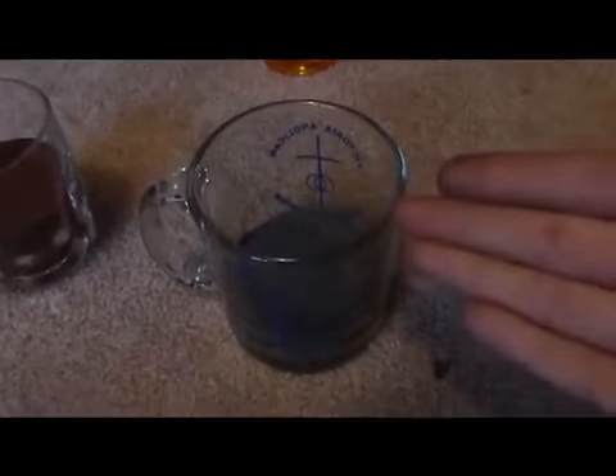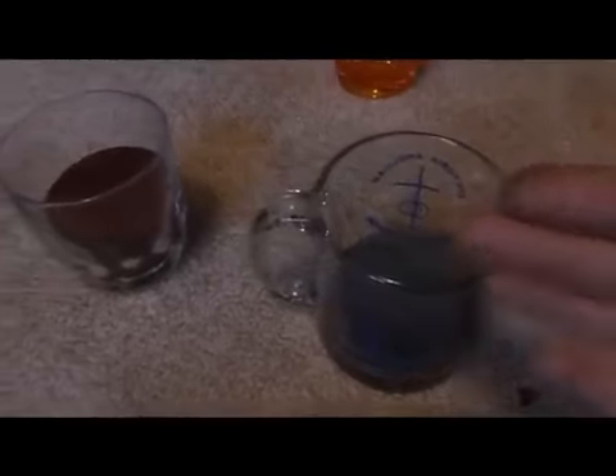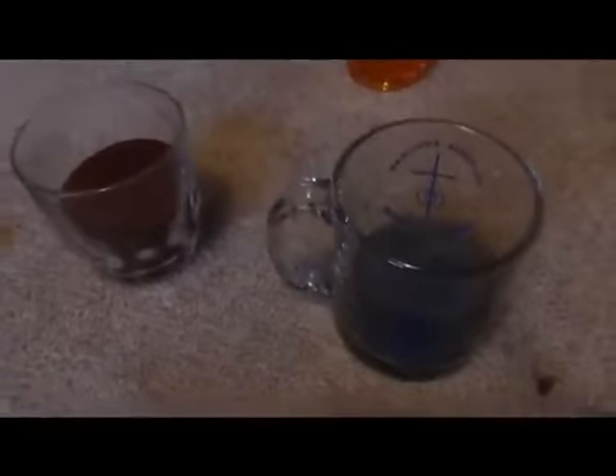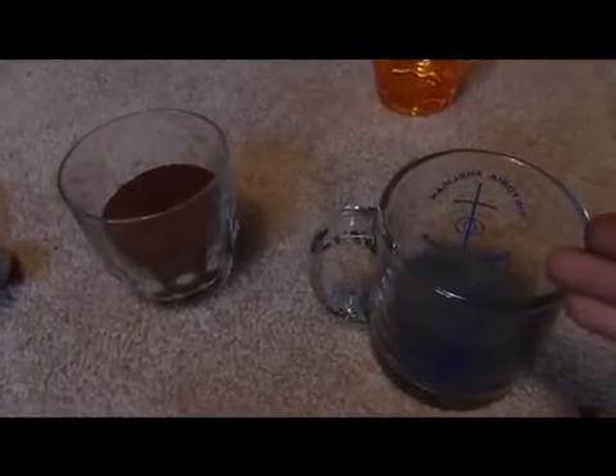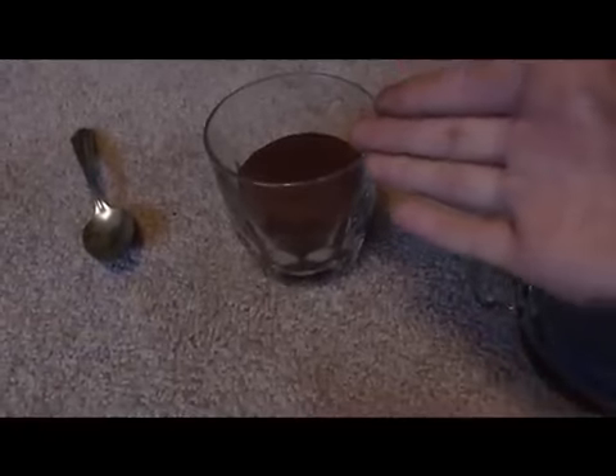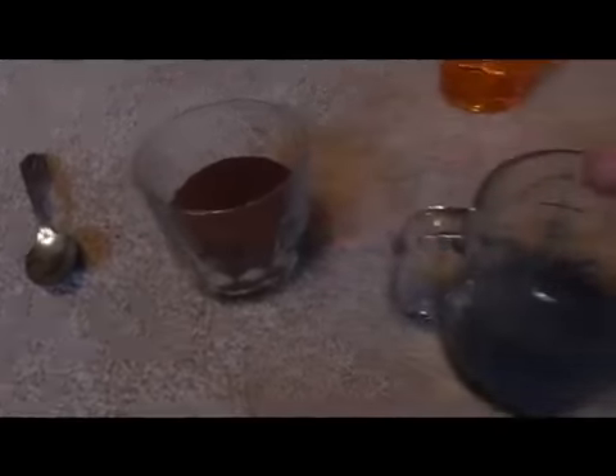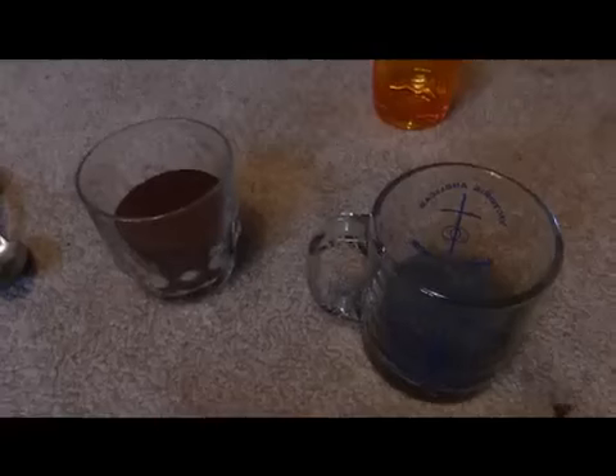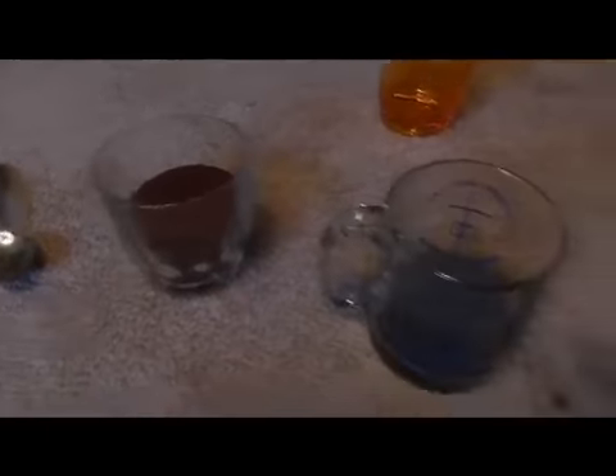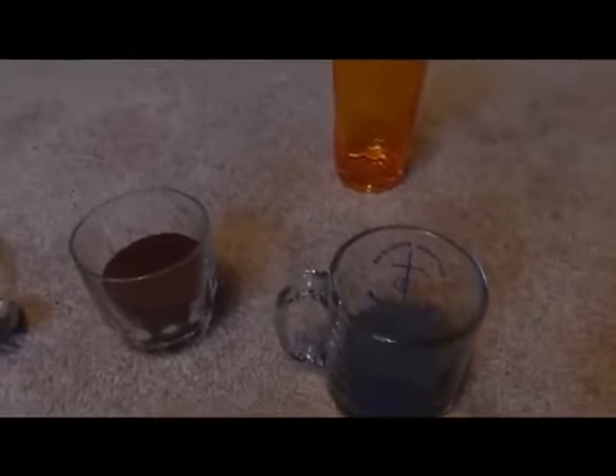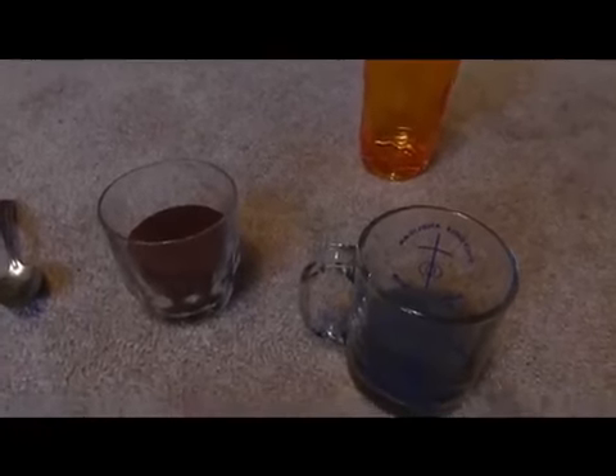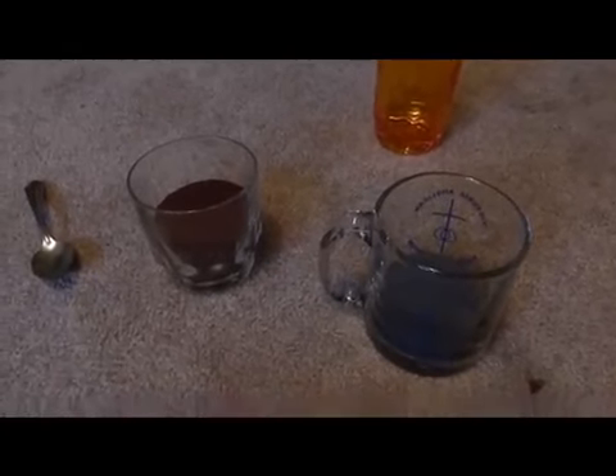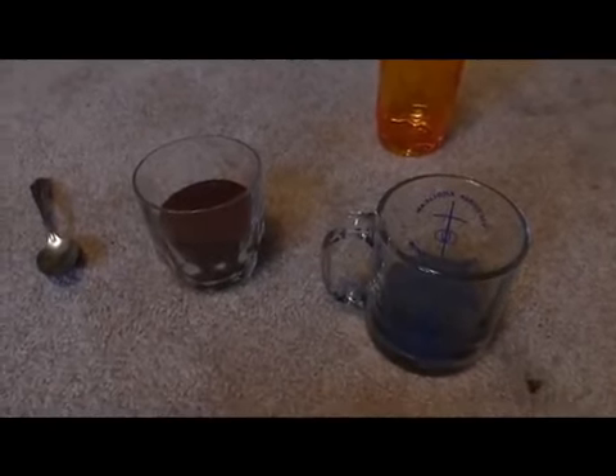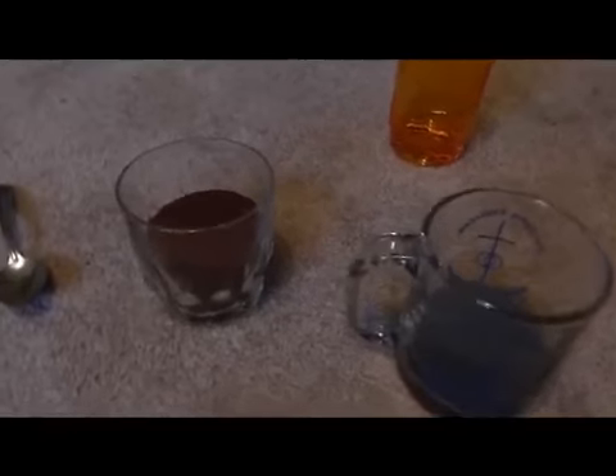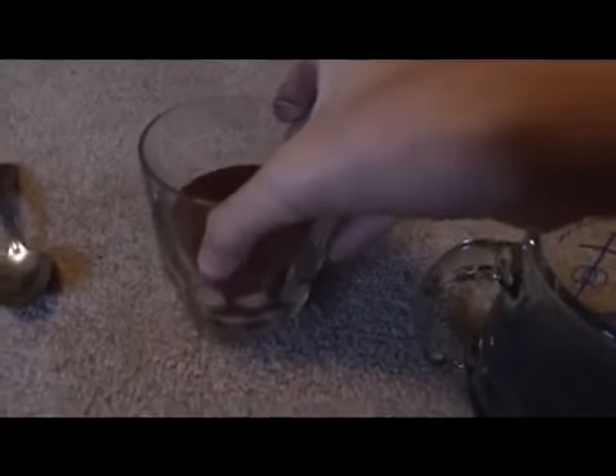When we combine the aluminum with the iron oxide and add heat, the aluminum takes the oxygen away from the iron oxide, making aluminum oxide, generating a lot of heat and making molten iron and molten aluminum oxide. So this is a very heat intensive process, and you should be very careful doing this, even if you do it at all.